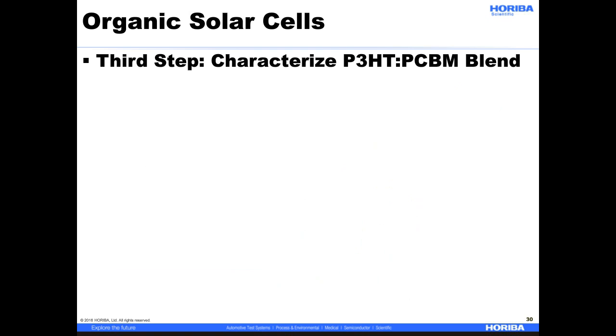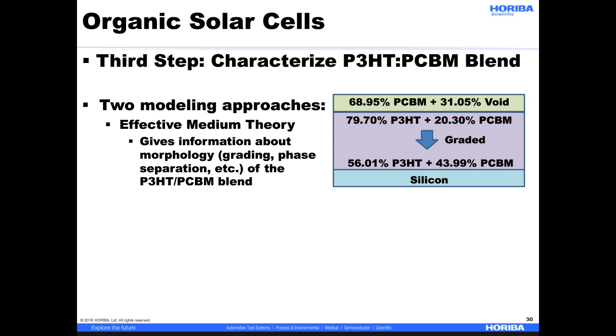Putting it all together, we want to characterize the blend layer of P3HT and PCBM. We can take two different modeling approaches here. The first is using an effective medium theory, where we have some blend on top of silicon, and this effective medium theory ends up giving information about the morphology, so the grading and the phase separation of these blend layers. Effective medium theory takes percentage of one material and adds it to percentage of another material to give an effective optical constant set for that layer.